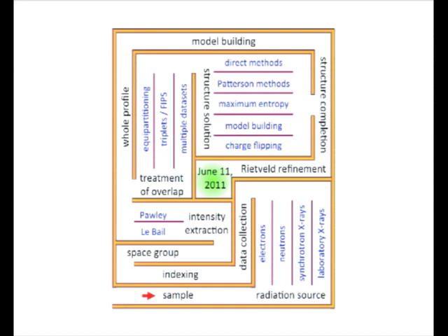The bottom line is, I think, allow me to paraphrase. Yeah, sure. I guess like single crystals, well, like protein, you have to validate your structure. The first validation is the Rietveld refinement. If your refinement is stable, if you don't have to fiddle around with it, you can be more confident than if you've done some things you really shouldn't do, which happens all the time. The other thing is the chemical sense of your structure in the end. How well does it agree with other characterization techniques? These are all things that you should always do when you've got a structure solution.